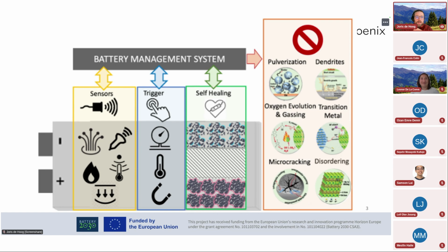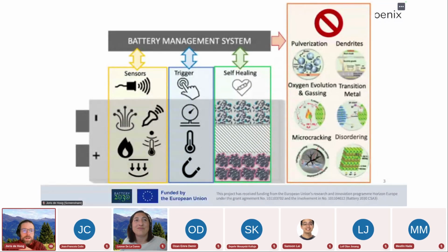Triggering of the self-healing functionalities is done by applying pressure, magnetic forces, and heat. And the self-healing is on all aspects of the batteries except for the separator. So we have developed or we are developing systems for self-healing on the cathode side, anode side, and the electrolyte in order to prevent the traditional degradation phenomena that we all know. So the pulverization of silicon anodes, for example, the formation of dendrites, oxygen and gas evolution, etc., etc.